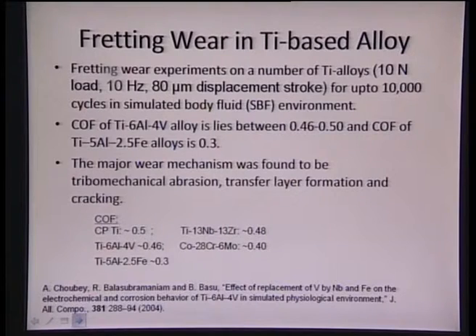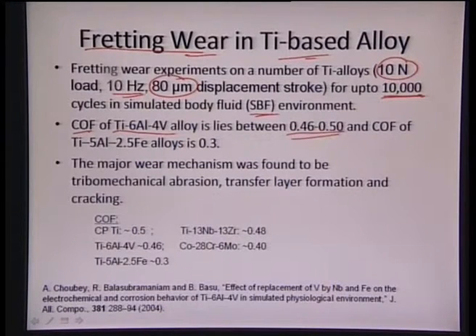And at the same time, they also did fretting wear of the titanium based alloys. So fretting wear was done using a 10 Newton load at 10 hertz and for a displacement distance of around 80 microns, and they went up to around 10,000 cycles, and all these studies were done under a simulated body fluid environment. So basically they found that the coefficient of friction for titanium 6 aluminum 4 vanadium lies between 0.46 to 0.5, whereas that of 5 aluminum 2.5 Fe falls within around 0.3. And they found that the major wear mechanism was tribomechanical abrasion, transfer layer formation, and cracking. So there are 3 steps to it. One is the tribomechanical abrasion, then the transfer layer formation, and then finally the cracking.